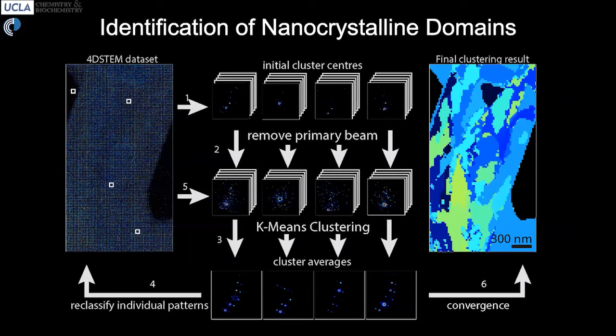We can cluster diffraction patterns, even weak ones, to combine all of those that are similar into groups, and then those groups can get averaged to produce cluster averages that you see down here. This can be done in an iterative fashion to try to optimize the grouping and identify the most coherent set of patterns that we can then group into relatively high signal to noise ratio patterns. So these patterns are not as noisy, and you can relatively clearly identify the type of lattice structure that is present and giving rise to these patterns.